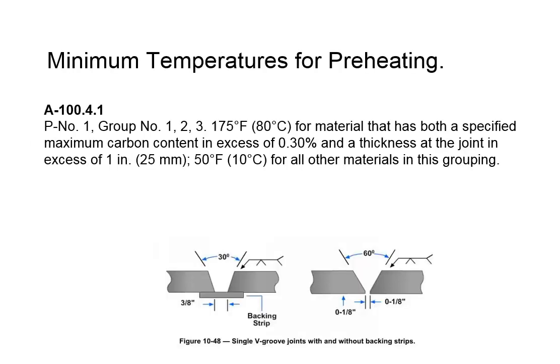I'm going to slam through some minimum temperatures for preheating. These are all from ASME Boiler and Pressure Vessel Code Section I. So P-number 1, which is mechanically similar to the Group 1 and Group 2 materials in AWS D1.1. This is the low end. The first thing they're throwing out there is the carbon content. If the carbon content is in excess of 0.3 and the thickness of the joint is in excess of an inch, you got to take it up to 175 degrees F before you start welding on it. But if it's less than an inch and it doesn't have a very high carbon content, you go to 50 degrees. It's pretty forgiving material.